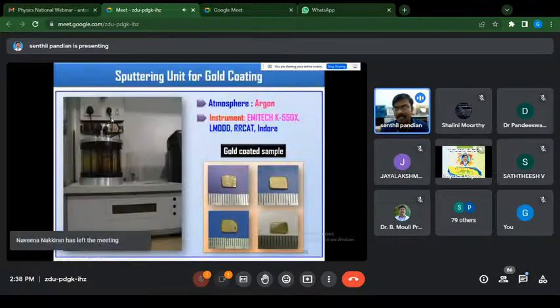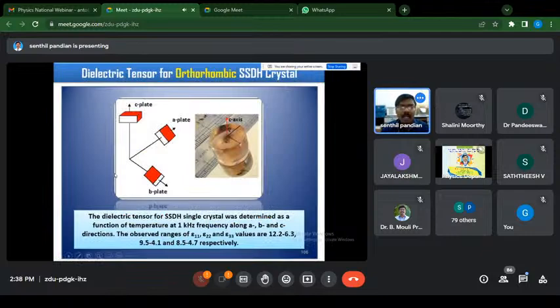And the dielectric tensor, dielectric constant, and dielectric loss values have been measured for the conventional and SR method grown crystals. And this is the gold coated TGS sample, and we have carried out the measurement with an RLC meter. The dielectric permittivity of crystalline materials is a second rank tensor. For orthorhombic crystals, there are 3 independent components. For monoclinic crystals, there are 4 independent components. So this is the SR method grown SSDH single crystal. Normally, from the crystal growth point of view, they grow the crystal, identify the dominant plane, and measure the dielectric constant and dielectric loss value of the dominant plane.